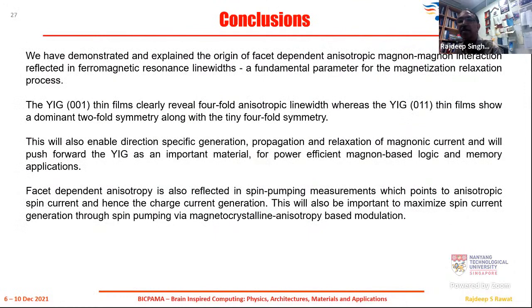So let me now conclude our talk. This paper is still being prepared and it will be submitted soon. So to conclude, what we have demonstrated and explained is the origin of this facet dependent magnon-magnon interaction in our case in YIG, and that will become very handy for those people who are trying to use this YIG as a spin wave conduit, because if they grow the material with different orientations, different amounts of spin waves can be generated, so they can be controlled in that sense.